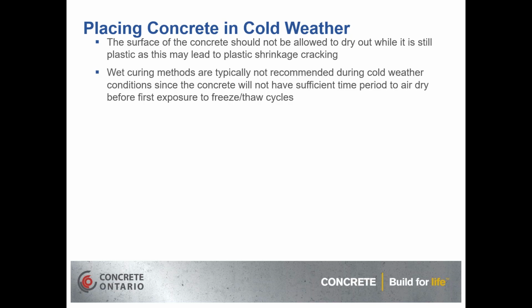Wet curing methods are typically not recommended during cold weather conditions. While they're ideal during the spring, summer, and fall, when ambient conditions dip below the freezing point, these are not recommended. We'll talk about some of the applicable methods for concrete protection and curing. The reason they're not recommended is that once the concrete is exposed to the cold ambient condition, it will not have sufficient time to air dry before exposure to freeze-thaw cycles. And if you don't allow the concrete to air dry appropriately, and the recommended period is typically 30 days or 1 month, it may lead to potential concrete scaling issues.